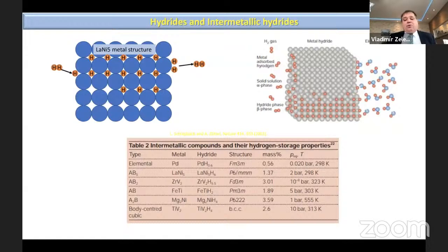The other possibility for storage of hydrogen is hydrides, either organic hydrides or inorganic hydrides or metal hydrides. It's not a new story because, as you know, some metals like palladium are able to absorb, so it's not adsorption, but absorption, a chemical process. One volume of palladium can absorb 700 volumes of hydrogen. And not only palladium, but also other metals or intermetallic compounds are able to absorb. One of the best known is the lanthanum nickel compound, which is used in batteries for a long time. It's very known.